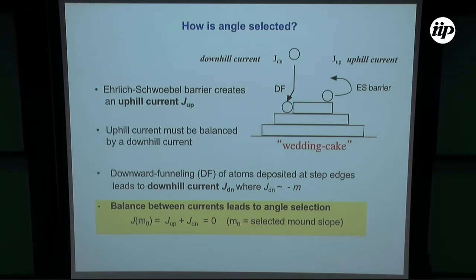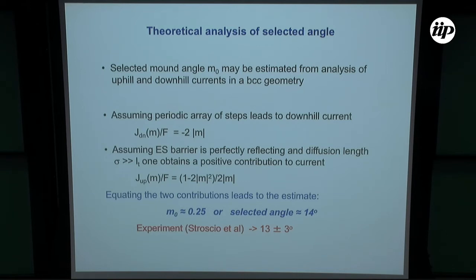And we can calculate that both in the simulations and in a simple random walk model. So I won't go through too much of the discussion. Basically, as I said, the downward current depends on the slope m. The higher the slope, the higher the downward current, which is negative. The upward current is a little bit more difficult to calculate, but initially it's proportional to the slope. It increases and then it decreases. And it is the sum of these two currents that selects the slope. When these two currents add up to 0, you get the slope. For the particular case of iron on iron, we find a value of about a quarter for the slope, which means the angle is about 14 degrees, in agreement with what we saw in the experiments.